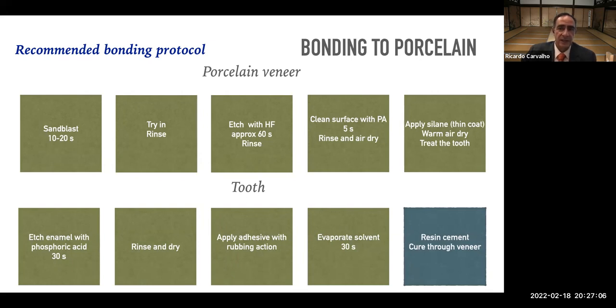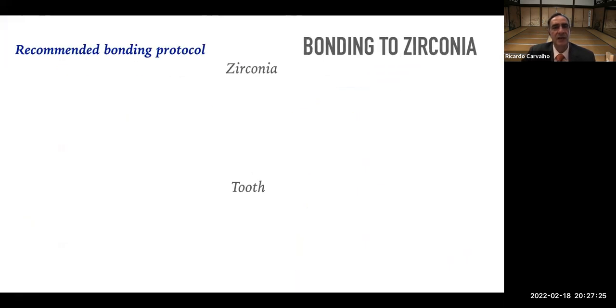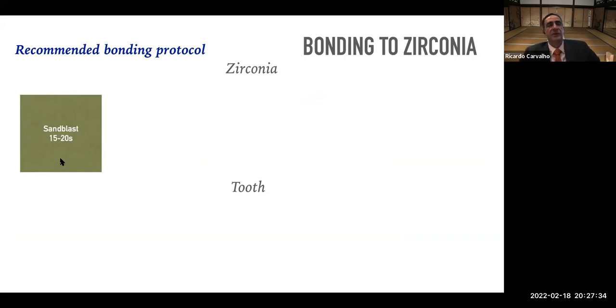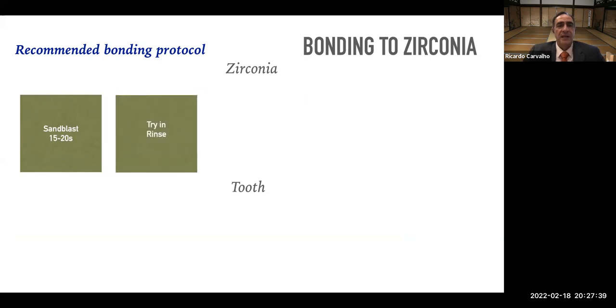And if you are dealing with a veneer, you can apply the adhesive, and then you can cure the adhesive and the cement all together through the veneer. But if you're dealing with a crown, I always recommend that you cure your adhesive first to ensure the bonding, and then you proceed with your cementation. But if we are dealing now with zirconia, again, there is a need for a sandblast. It's probably more important for zirconia than it is for veneers or feldspathic.